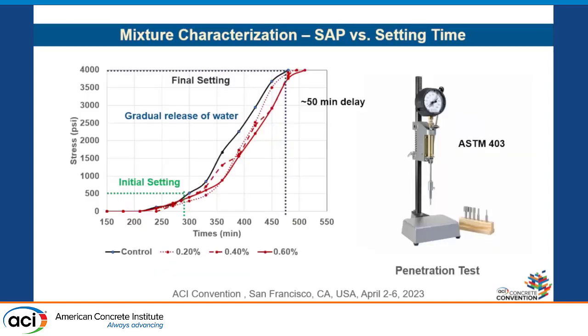And we observed the same effect on the setting time. As you see, we used the penetration test ASTM C403 to measure the setting time, and you see 500 psi and 4,000 psi as per ASTM are used to tell what is the initial setting time and the final setting time. And again, you will see that the setting time is being delayed because of incorporation of SAP.